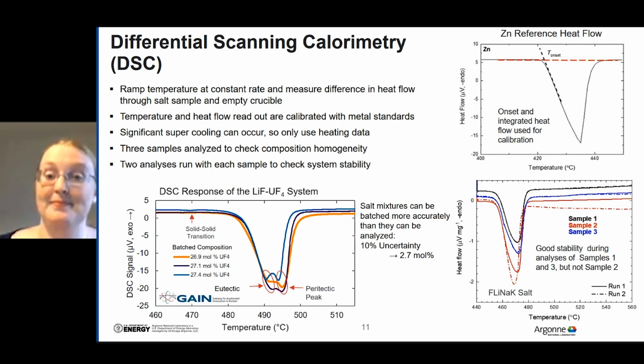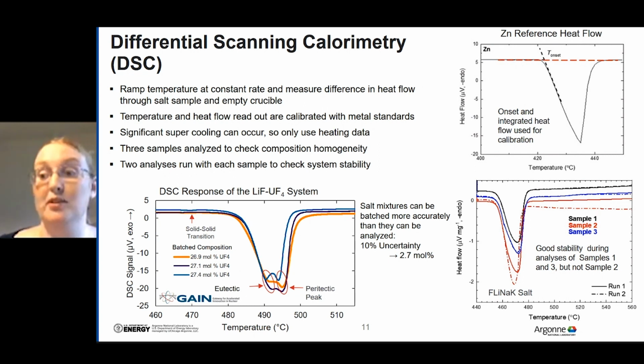What about fuel-bearing salts throughout their life? Obviously, they're going to develop fission products, they're going to develop contaminants, and I think once we develop these consensus standards through ASTM, we can then move on to more complex mixtures. Maybe that's where modeling can come in to help us with the addition of those impurities and their effect. Do you use gold-sealed crucibles for the DSC? Absolutely. We find that to be an important quality control factor.